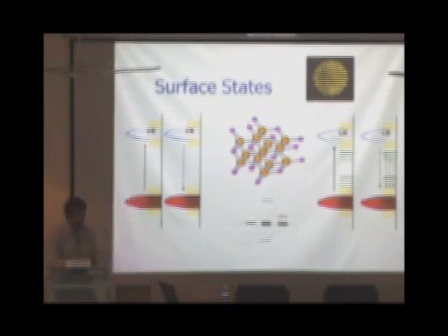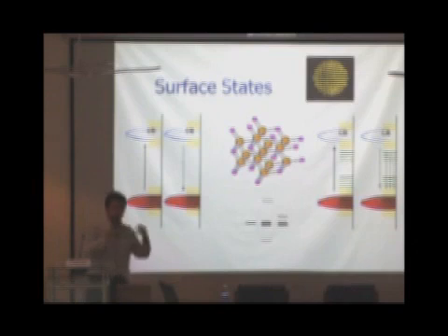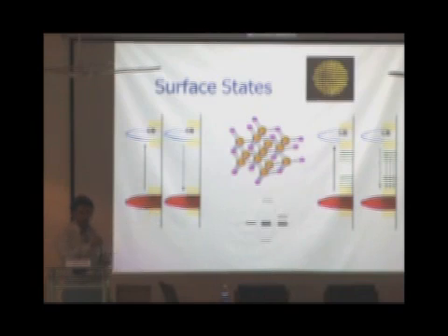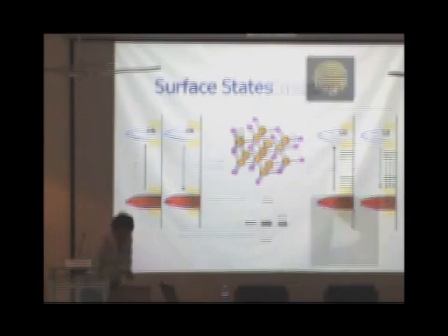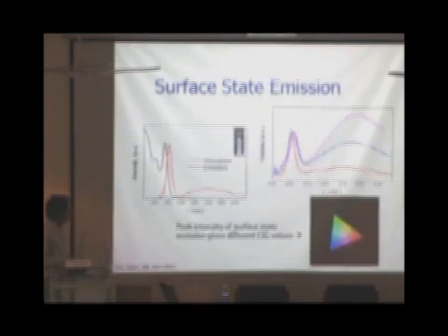So what I have to do is cleverly make a particle with lots of surface states, right? And choose the emission of the band edge to be somewhere on the edge of ultraviolet blue. So you have a sharp ultraviolet blue peak, and when these states come in, they will automatically be lesser in energy, so they'll take care of the green, yellow and red regions. And if I can tune that emission, I could get very good white light emitting particles over here.